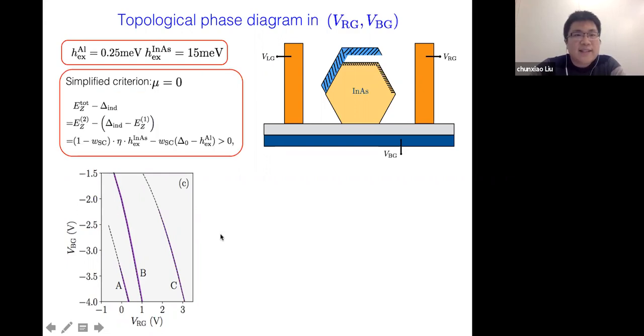So we can understand it with a simplified topological criteria. Because now mu is 0, the criteria is actually the direct comparison between the total induced Zeeman energy and the induced superconducting gap. A little manipulation of the equation shows that in the end, it depends on the hybridization of superconductor and semiconductor of the subband mode, and also on the direct magnetic efficiency eta, while other parameters are fixed. And it turns out that this hybridization and efficiency will change with the gates. So that will lead to topological phase transition along this equal potential line. So let's look into more details.